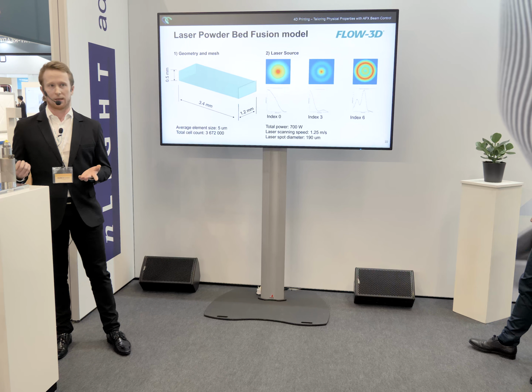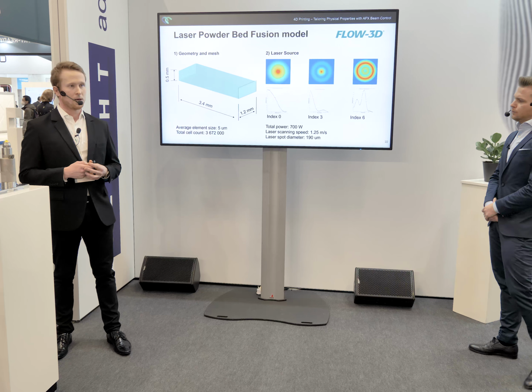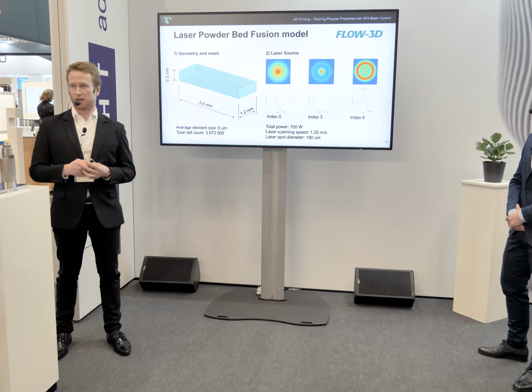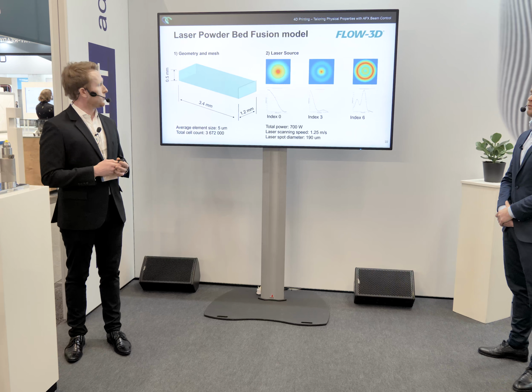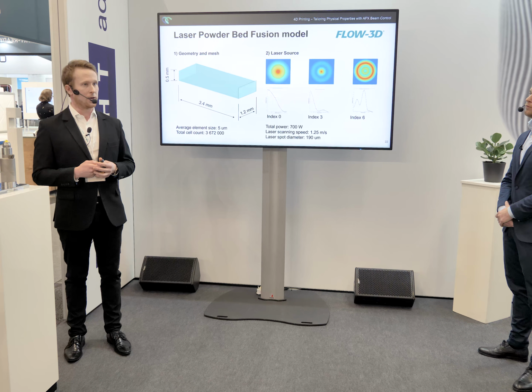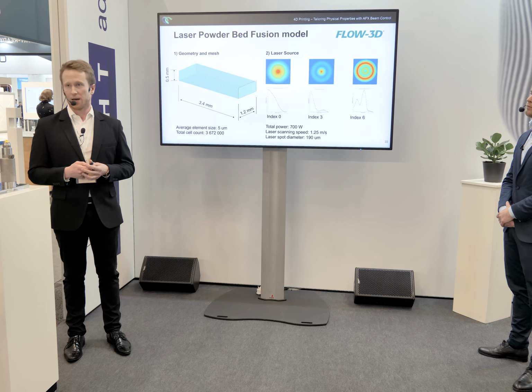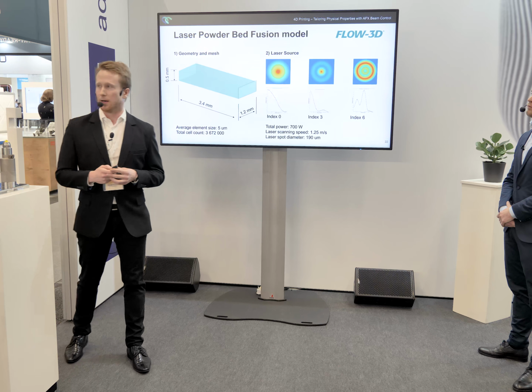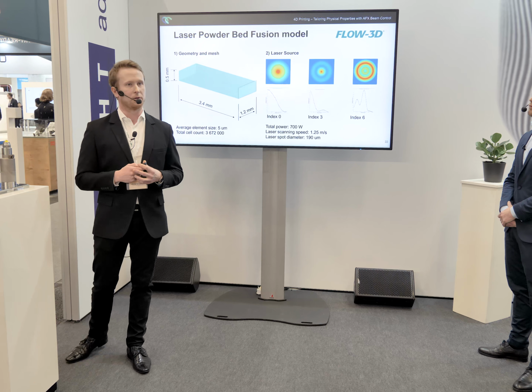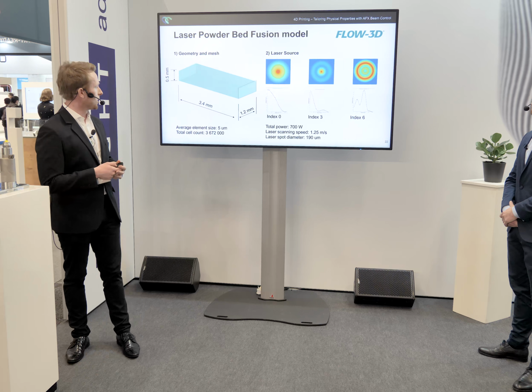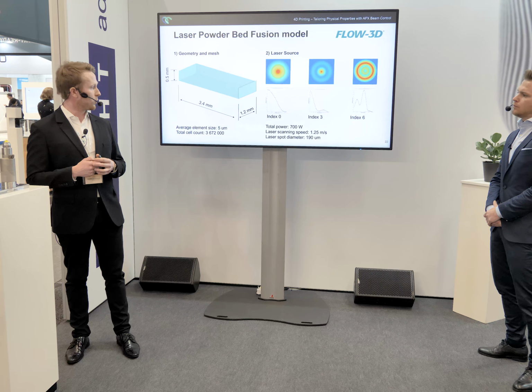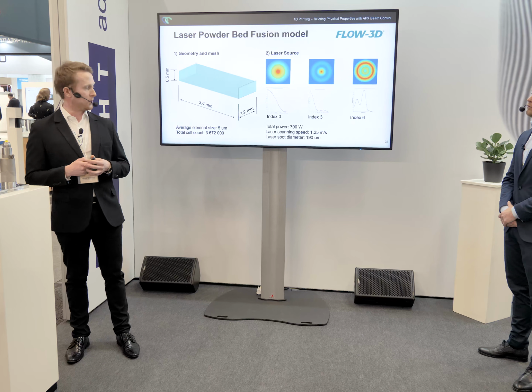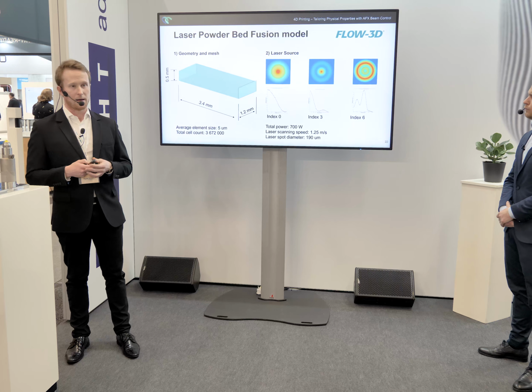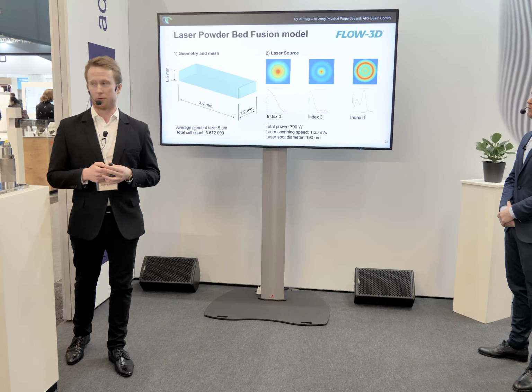In the software itself, we can, of course, implement the different heat flux distributions in the radial direction. So in this case, for this project, 3 different indices were chosen. And of course, we kept the other laser parameters the same as in the experiment, which is a total power of 700 watts, a scanning speed of 1.25 meters per second, and a laser spot diameter of 190 microns.